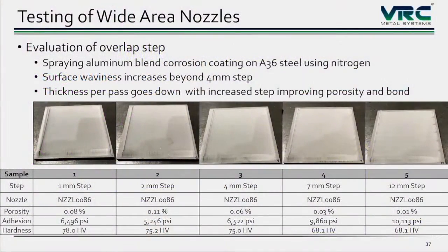Let me go back here. One thing you'll notice that's very clear is that your bond strength goes up as you go to the larger step. That's because our thickness per pass is going down, right? So we know that thickness per pass being thinner is always better for bonding and for porosity. You can see the porosity got lower too there.